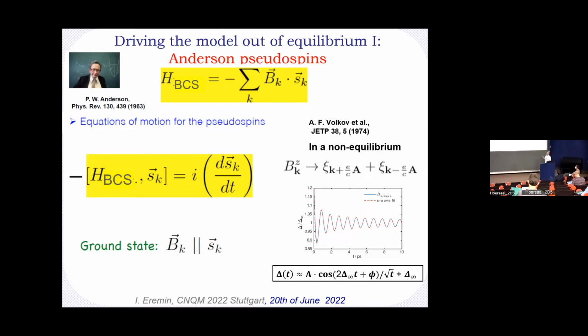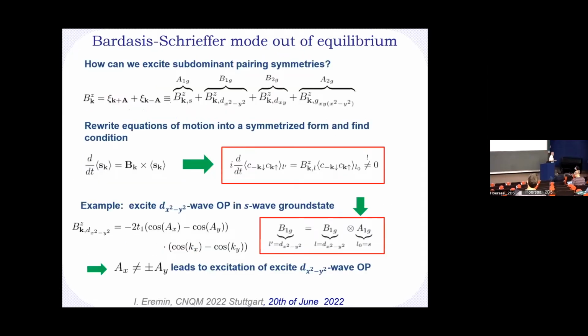Okay, so the first way to look at it, in principle, you can start with a description in Anderson pseudospins. You write your Hamiltonian, which then looks like a standard Landau-Lifshitz type equation for the pseudospin basis. And what is important is that you can couple easily to the electromagnetic vector potential, because it couples to the pseudo Z component of the magnetic field. So this is sort of known stuff, and in principle, it is known that once you introduce a quench in an S-wave superconductor, or via the electromagnetic field, you generate the Higgs oscillation and also the oscillation of the quasiparticles. But now let's move to what's happening in the subdominant case.